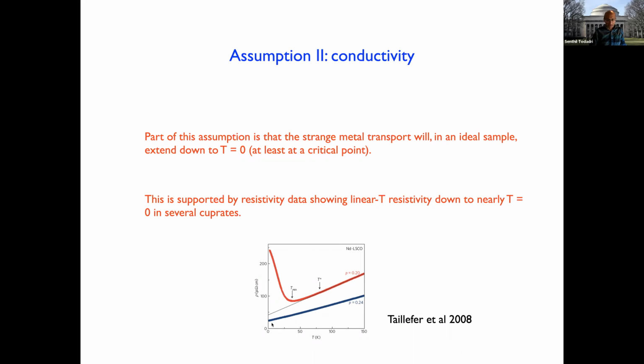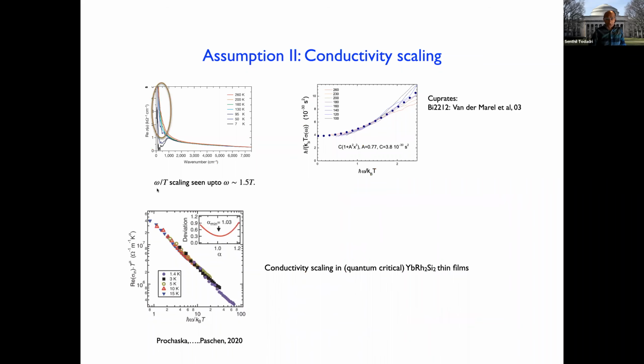And this is supported by the resistivity data that shows linear T resistivity down to zero temperature if you manage to suppress the superconductivity with the magnetic field, as people have done in some samples. So let me show some of the evidence for conductivity scaling. It's a bit complicated. So this is a plot of the real part of the conductivity, the dissipative part of the conductivity, as a function of, you should just think of this as frequency. The first thing you notice is this long tail, and this tail goes up to about an electron volt. It probably has nothing to do with any delicate low energy physics. So the focus is going to be on what happens at lower frequencies.